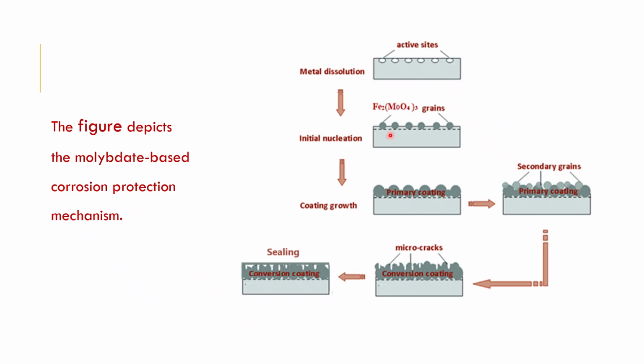When this substrate is dipped into the solution, on the active site the iron molybdate is formed. How? Iron which is on the surface dissolves into the solution, and the same thing gets deposited over the surface. See, now we have the nucleation process taking place. Once the nucleation has taken place, in the sideways also, the iron molybdate starts growing up. So it forms one single primary coating. You can see in the third figure. Okay, one single primary coating.